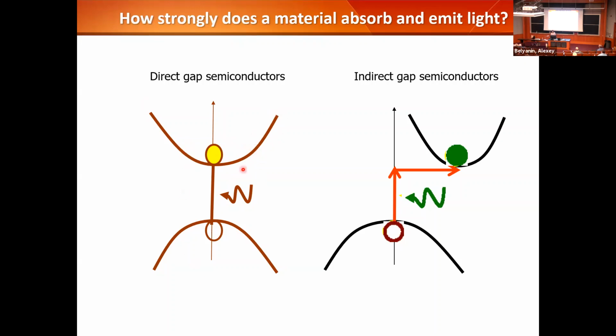And if you have a direct gap semiconductor, it only means the bottom of the conduction band and the top of the valence band are aligned, where they share the same momentum. So a photon carries very small momentum when you compare to the Brillouin zone, which you need to consider when you describe the band structure of a material. The Brillouin zone has a size pi over a, a being the lattice constant. But if you think about the momentum of a photon, the wave vector of a photon is 1 over 500 nanometers, for example. So a photon carries momentum that's very small compared to the entire Brillouin zone. As a result, any optical interaction, either absorption or emission, is what we call a vertical transition. So there's no change in the momentum in the Brillouin zone.